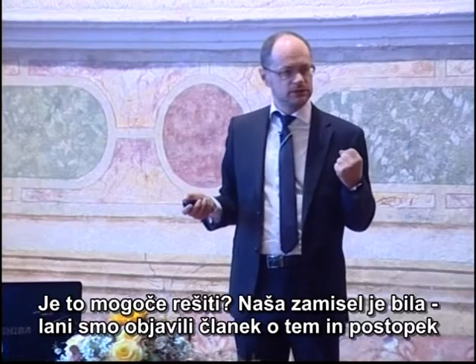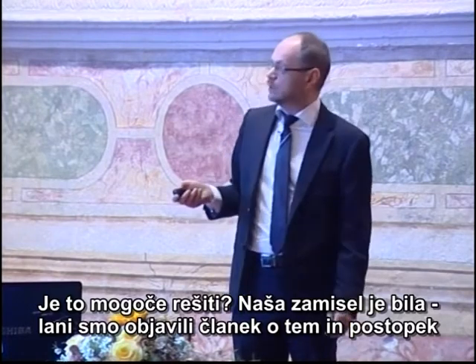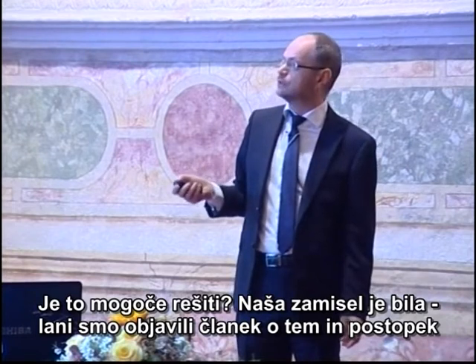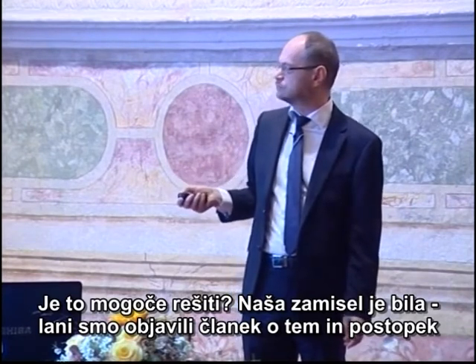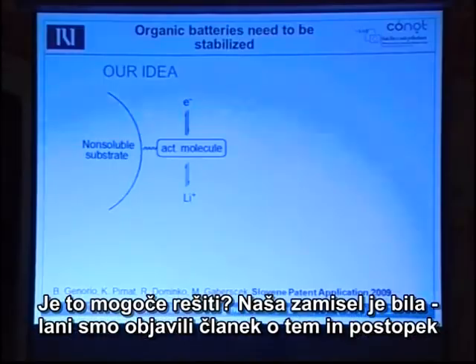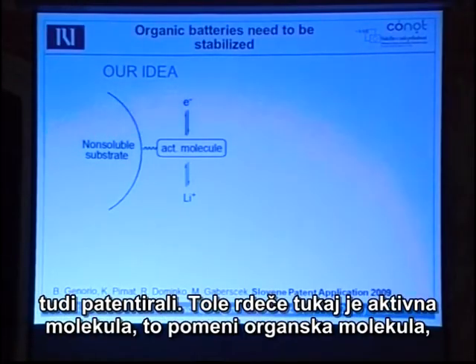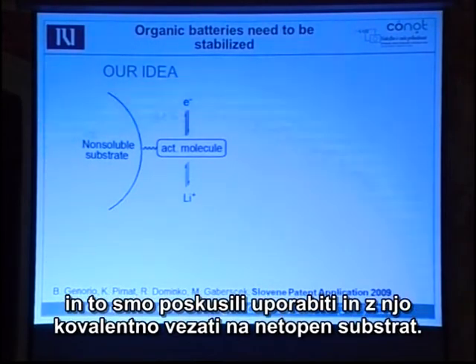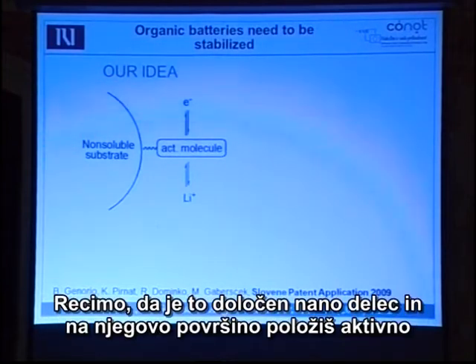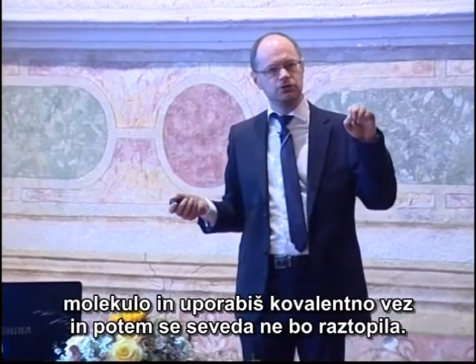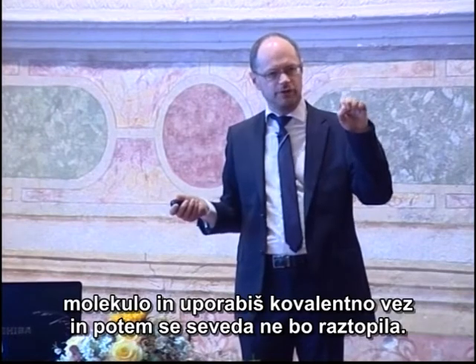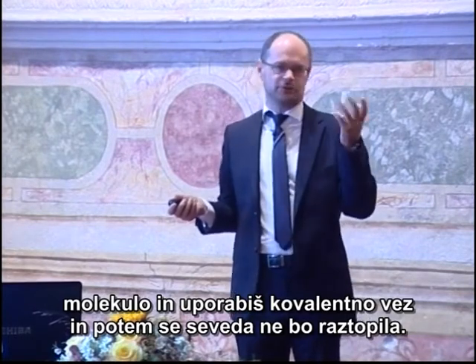So how do you solve this? Can this be solved? We tried to do it. This was our idea. Last year, we published a paper on this and also a patent. Our idea was to use this red one as active molecule, which means organic molecule, and you try to bond it covalently on a certain substrate. Let's say that this is a certain nanoparticle, and you put this active molecule on the surface of a nanoparticle, and you use covalent bonding. And if you covalently bond this, it will not dissolve, of course. It cannot.